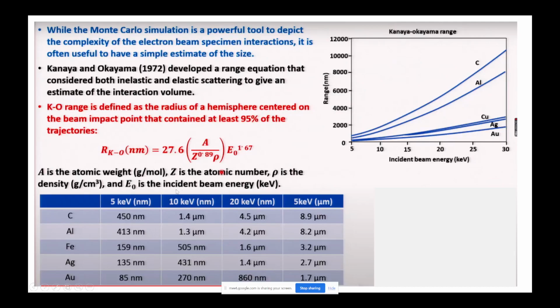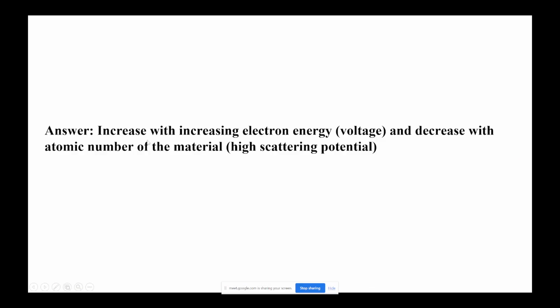And yes, this is the plot for that also. Here, your voltage is increasing, and the higher the voltage, when you increase the voltage from 5 to 50 kilo electron volt, the interaction volume is increasing. But when you go from the lower atomic number to the higher atomic number, the interaction volume is decreasing. So yeah, that's fine. So you are right.